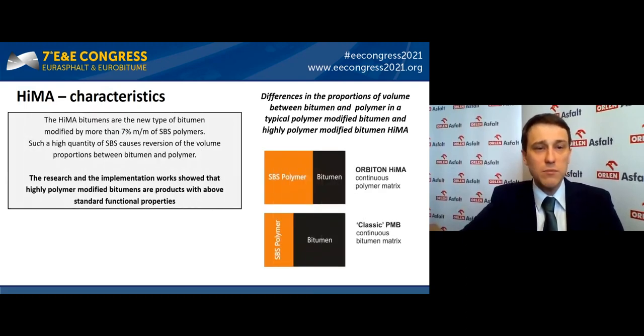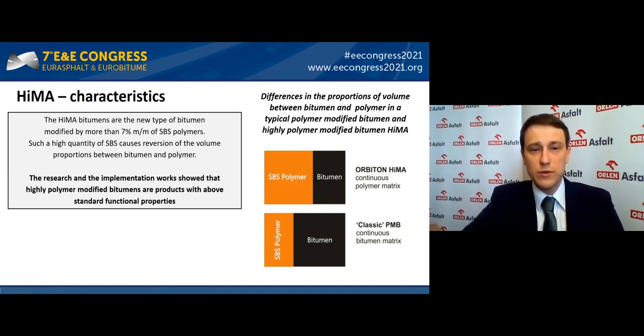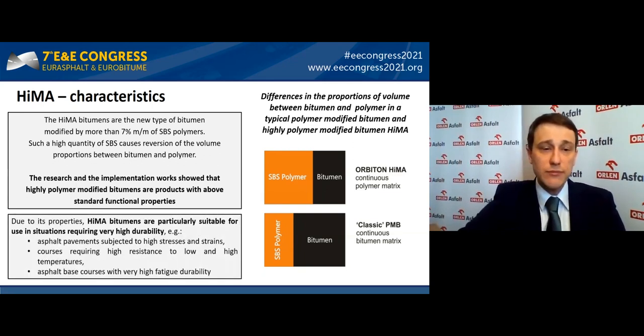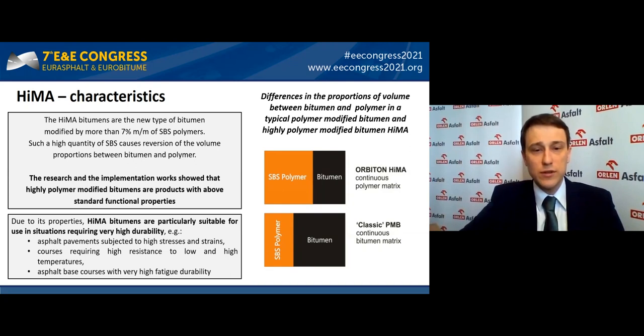To model real compaction and paving on site in the laboratory, a gyratory compactor was chosen. Tests were conducted according to EN standard. Two parameters were targeted: void content after the first gyration and compactability coefficient k. To facilitate comparison, the further analysis used the indicator V50 — calculated void content after the 50th gyration — and a second parameter, the Construction Energy Index (C index), calculated as the area below the compaction graph between zero and the 8th compaction cycle, representing the work performed by a typical paver during placement but before use of the roller. The threshold is 4.8% void content, representing 98% compaction ratio.